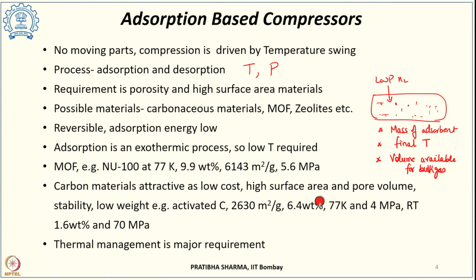That result is at 77 K. However, at room temperature, only 1.6 weight percent can be achieved at 70 MPa. This clearly shows the advantage of reduced temperature in case of adsorption based compressors.